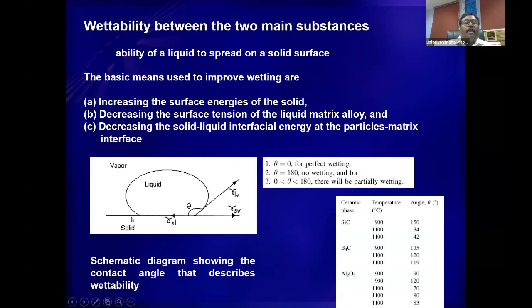The wettability can be decided with the wetting angle. So you have a tension vector: the surface tension vector of solid-liquid and the surface tension vector of liquid-vapor, and the angle between them. If this angle is 0 or close to 0, we call it perfect wetting. Preheating the ceramic particle to 1100 degrees centigrade gives an angle of 42 degrees, compared to 900 where you have an angle of 150. Therefore, preheating the particle before adding it into the melt helps to improve the wettability.